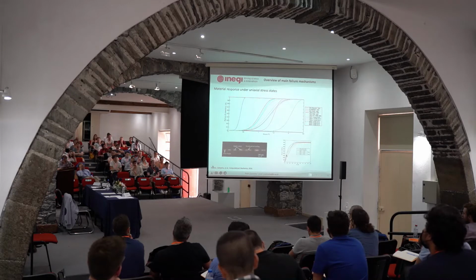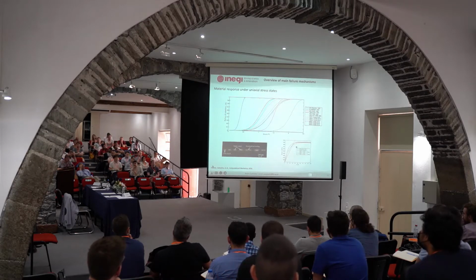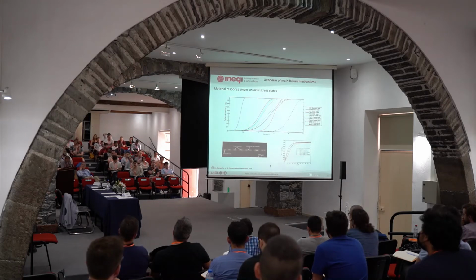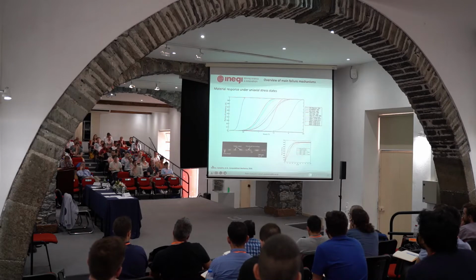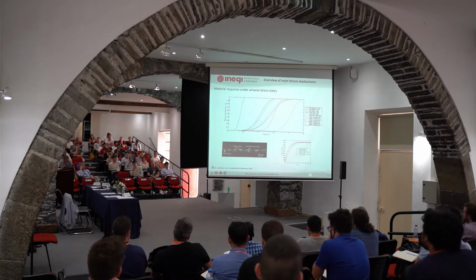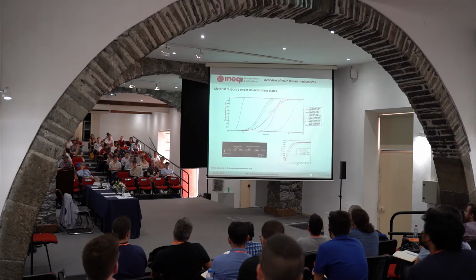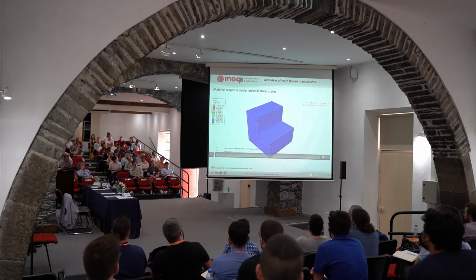So what we can see from simulations and also from other models is that, for example, if you take this position as the position of a fiber fracture, and this is a non-dimensional dimension associated with the axis of the fiber, this is stress. Of course, this is a traction-free crack. Stress is zero there, but you can see that the fiber is picking up stress again. So you have this shear-like process that reloads the fiber, and that means that the fiber picks up the load at different locations, and then it has an additional weak spot, and then it breaks, and this continues until it saturates.